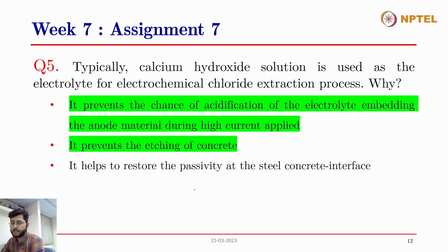And that will cause the acidification of the electrolyte. But if a calcium hydroxide solution is used as the electrolyte, then calcium chloride will be formed, and therefore the acidification of the electrolyte will be prevented. So this is a true statement.